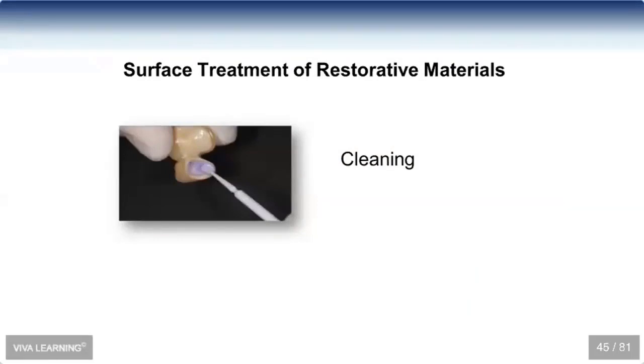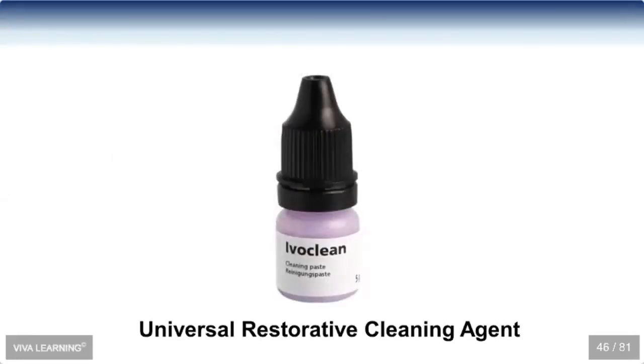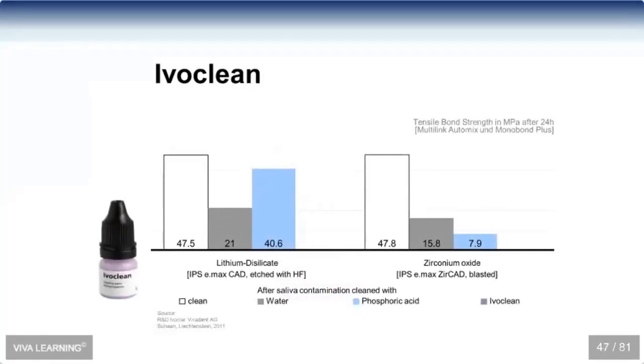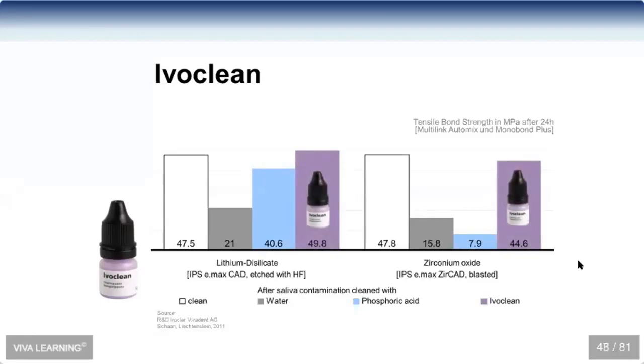We're going to clean the materials chairside. We want to decontaminate these materials, so that's some IvoClean being used. That's a universal restorative cleaning agent that can be used on all crowns. And it's interesting to see, I mentioned earlier about the debonds of zirconia crowns in Rella's study, and how we didn't realize at the time that saliva, specifically the phosphate groups in the saliva, would contaminate zirconia and lead to these kind of issues. And it's a much bigger problem for zirconia, certainly, than it is for lithium disilicate.